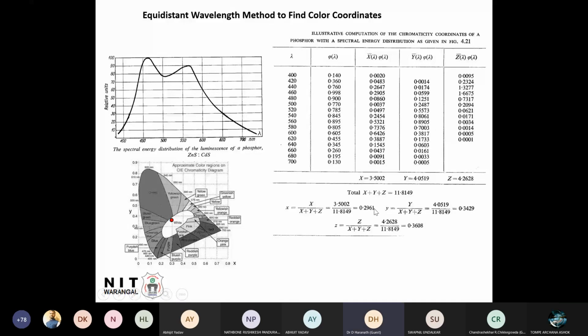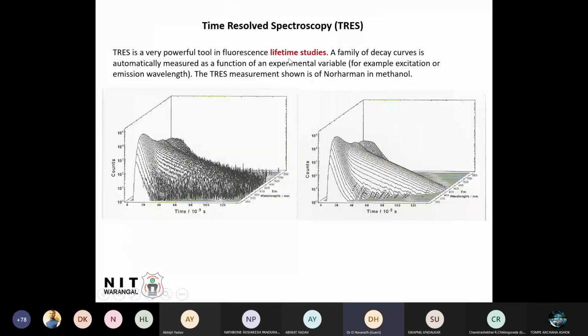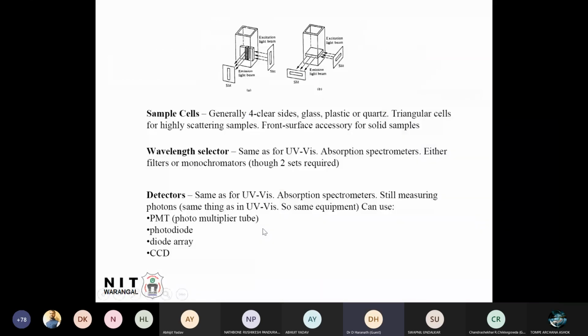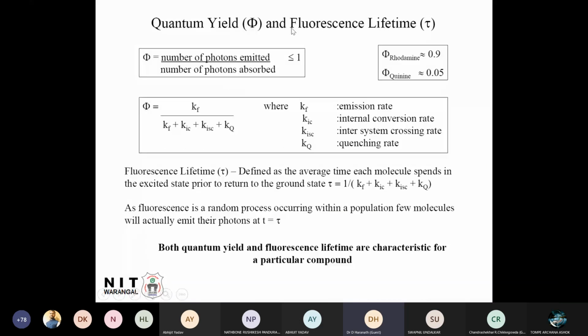Time resolved spectroscopy, as I told you, gives the lifetime measurement: how much time the electron rests in the higher energy state. You can determine it using liquids also. The other way is quantum yield or quantum efficiency. You have to take some known material with a quantum efficiency of 0.9, which is very good. 0.9 is 90%. You measure the quantum efficiency using this one, then replace it with your phosphor and correlate.